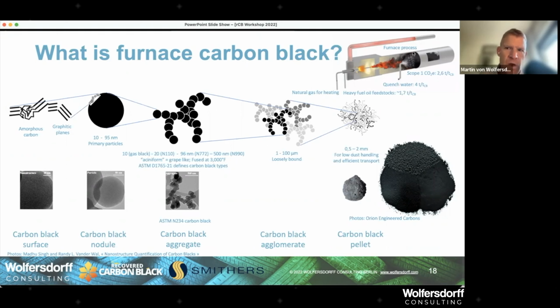And they could do so because the cladding, which are refractory materials, has been improved to withstand even 2,000 degrees Celsius. And so we have a lot of feedstock for 1 ton of carbon black. We have a lot of quench water, 4 tons of quench water per ton of carbon black. And it's not surprising that in the scope 1 emissions, direct emissions from production, carbon black has 2.6 tons of carbon dioxide equivalent per ton of carbon black.